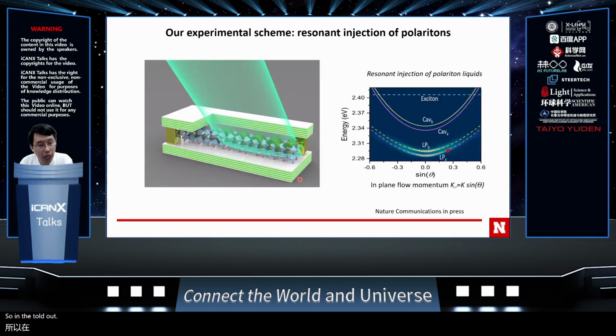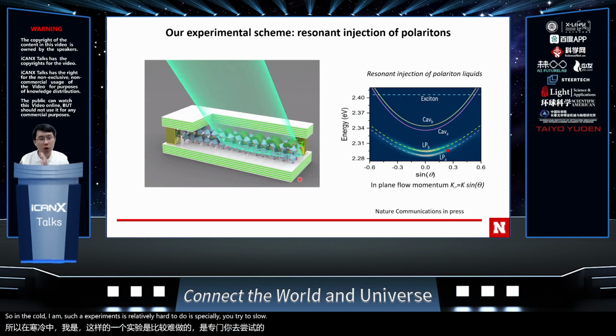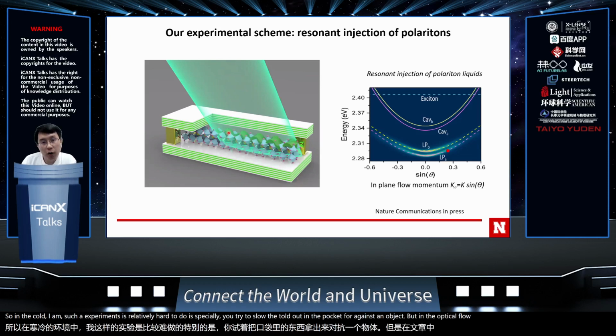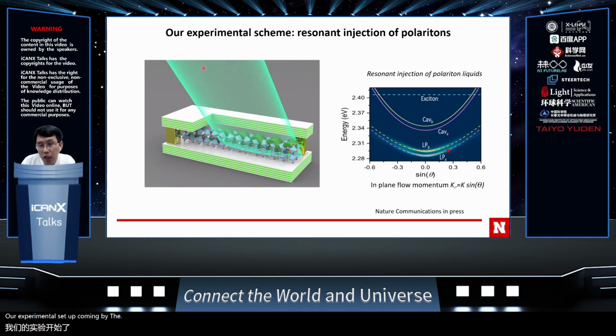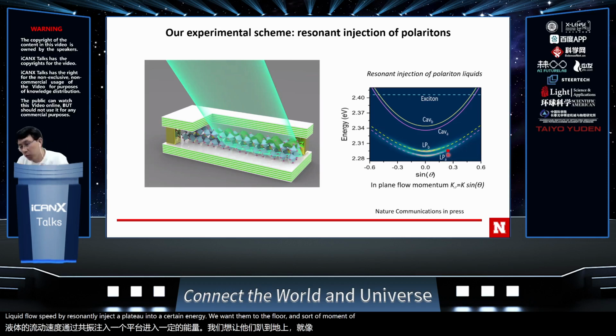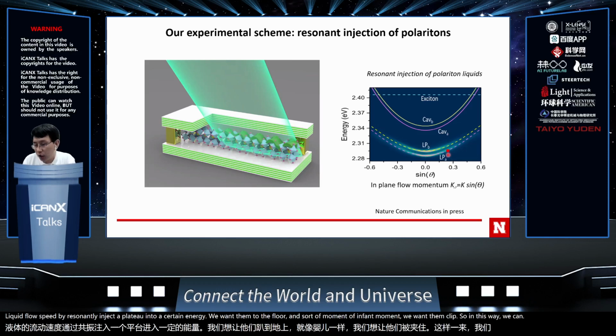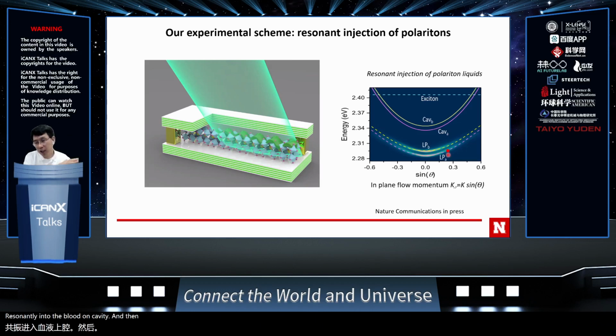In cold atoms, such an experiment is relatively hard to do, especially trying to flow the cold atoms in a trap against an object. But in the optical polariton case, our experimental setup can be quite easy. We control the polariton liquid flow speed by resonantly injecting the polaritons at the energy we want and the in-plane momentum we want them to flow with. In this way, we can control the flow velocity simply by injecting a femtosecond laser resonantly into the polariton cavity and then letting it evolve freely to see the superfluidity behavior.